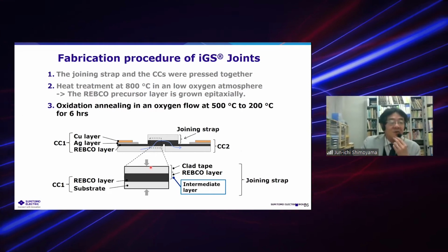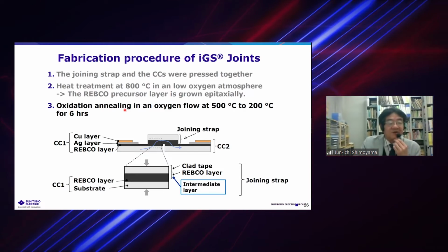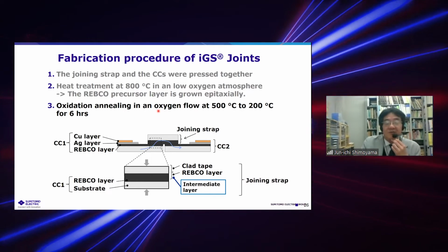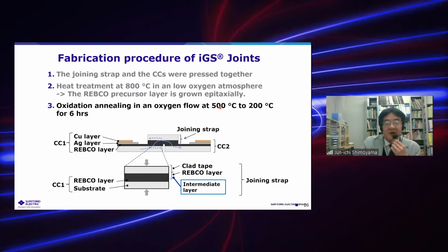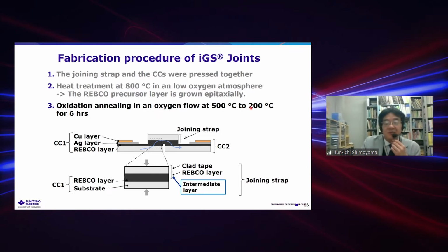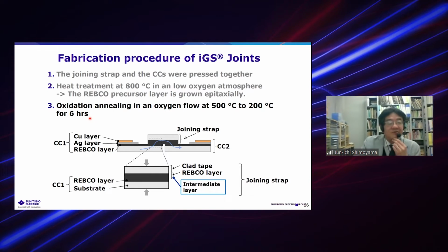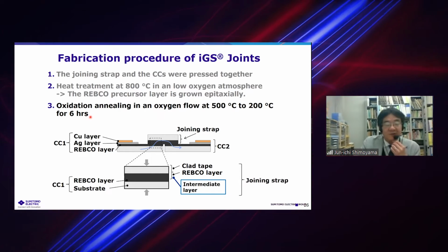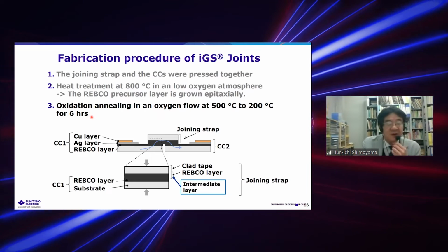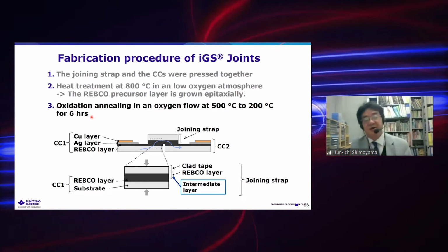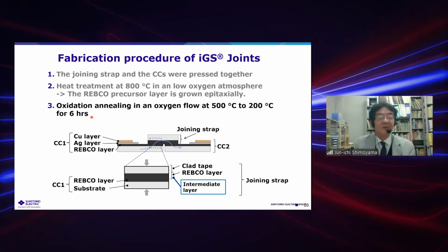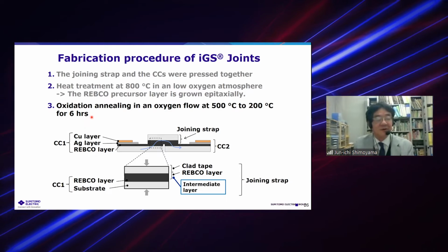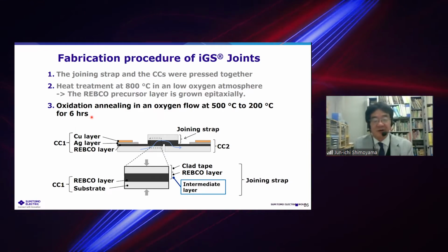In this case, oxidation annealing in flowing oxygen at 500 degrees C to 200 degrees C for 6 hours is enough to introduce oxygen to make 90 Kelvin class superconductors, due to the presence of the small angle grain boundaries.